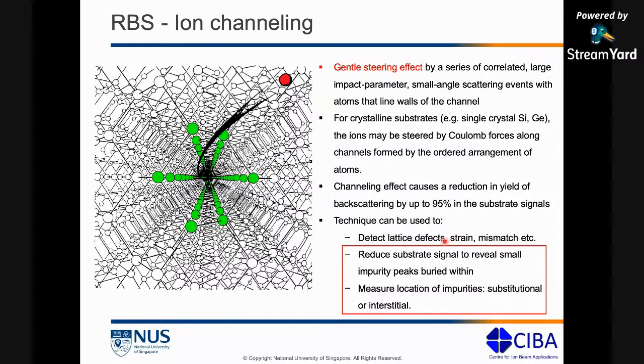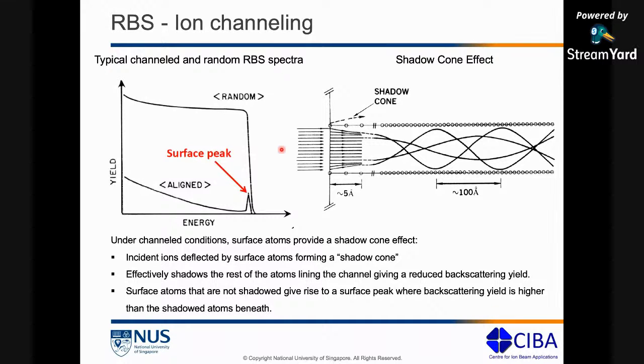Okay, so if you look at ion channeling, this is what a typical RBS spectrum looks like. This is a typical random RBS spectrum. When I say random, I mean that your substrate is either not crystalline, that is, it's amorphous, or it's a crystalline substrate, but you have not aligned the atomic rows to the incident ions, which is why you get a huge backscattered signal. Now, when you have channeling, what's going to happen? Most of the incident ions are going to go into the channel, and what that is going to do is give you a significant drop in your backscattered yield. So this was a backscattered yield in random mode. But once you have aligned your channel to the incident ion, this is what your backscattered yield looks like. So there is a significant drop, right?